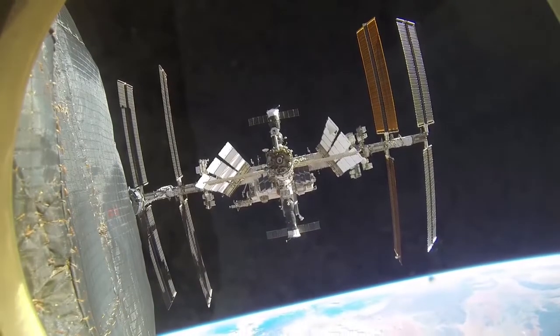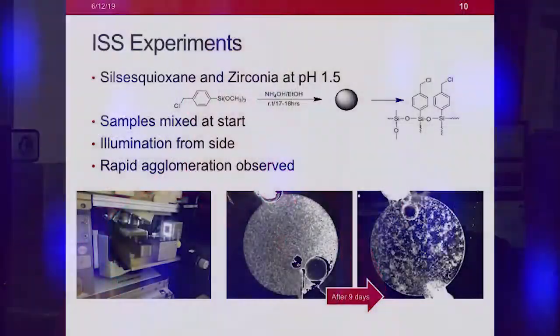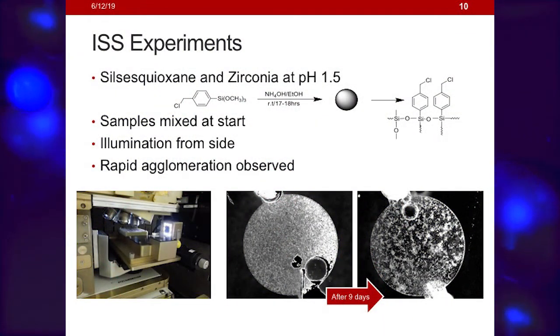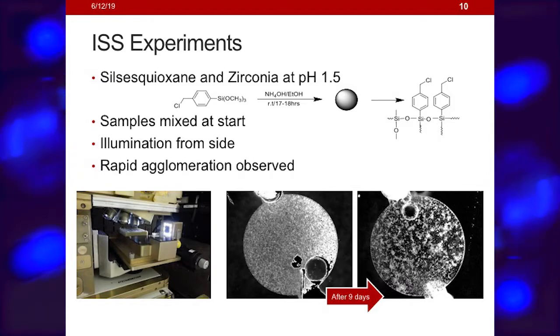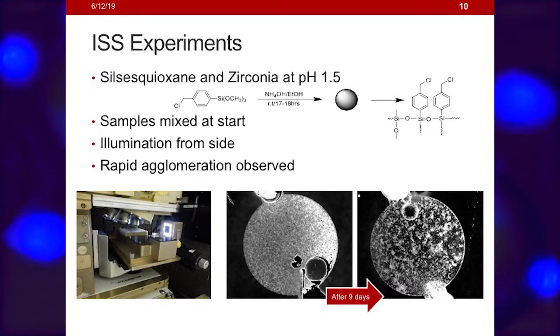The microgravity environment is important because when we look at these types of systems aggregating in a gravity environment, what tends to happen is the larger particles will artificially densify as they drop to whatever base you have and push out the small particles. So when I do get a crystal to finally form, I'm only getting a crystal structure of that large particle. The small particles tend to stay in suspension.